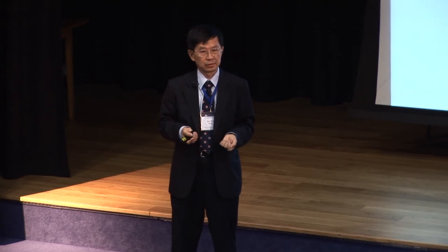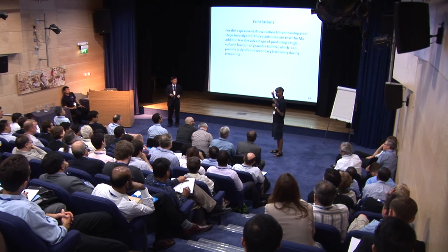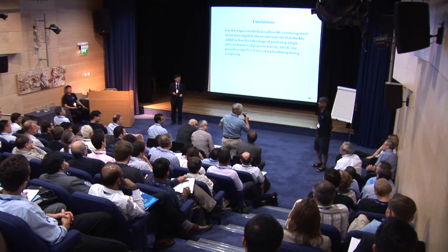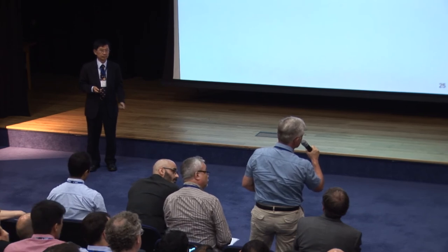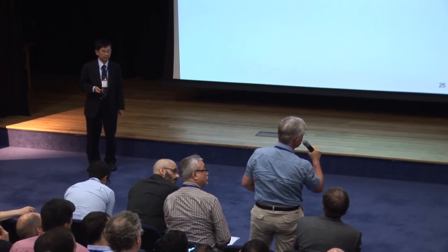Someone should comment on the fact that niobium and molybdenum dissolve in the same carbide, whereas we know that doesn't happen with titanium and molybdenum. Do we know whether molybdenum should be soluble in niobium carbide? Yes, I know it, because we used, for example, niobium in high-speed steels, and complex carbides were formed which contain both of the elements.